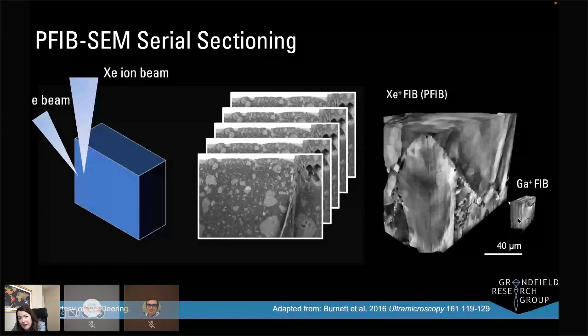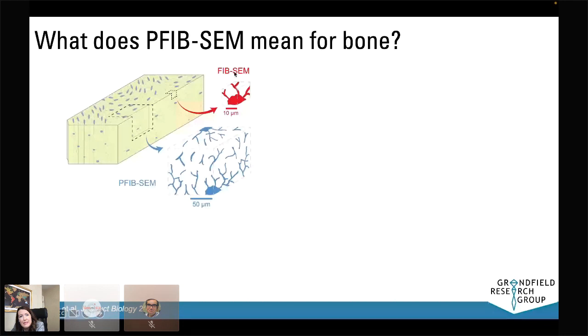So for bone, that means something quite exciting: where a traditional FIB-SEM with gallium might show part of a cell and some cell processes, when you apply plasma FIB-SEM, you can start to see several cells and the interaction between the cell networks over a much larger volume.